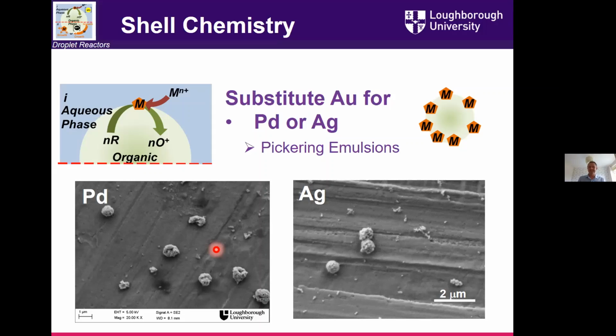Whilst the gold is really interesting, I wonder if something else would work a bit simpler for me. And we tried some palladium and we tried some silver. So here's that same shell chemistry now for two different metals. We haven't changed anything else. We kept the droplets the same. We've kept the electron donor the same. And this is kind of what I expected to see in the first case. If I'm honest, this was something that kind of looks like a droplet.